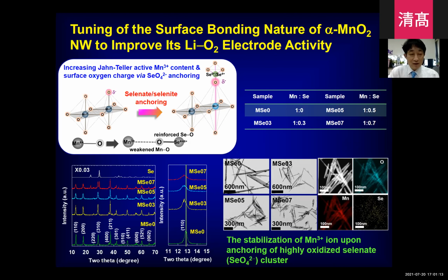So if you consider the bond competition, if you anchor the highly oxidized selenate nanocluster, we can form a very strong selenium 6+ oxygen bond. So it leads to the elongation of the neighboring manganese oxygen bond. In that way, we can stabilize the Jahn-Teller active MnO6 octahedra. So we synthesize several selenate anchored manganese oxides with variable selenate content.